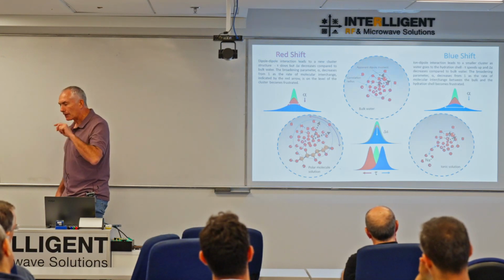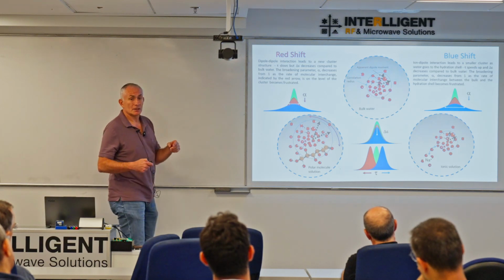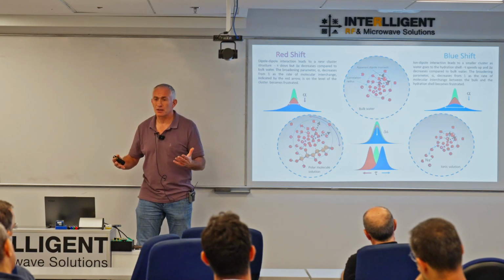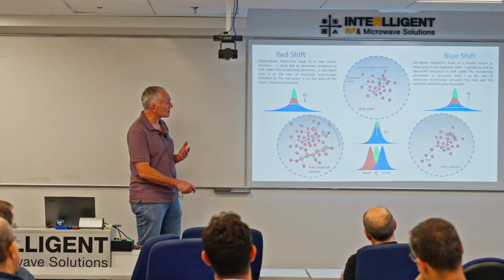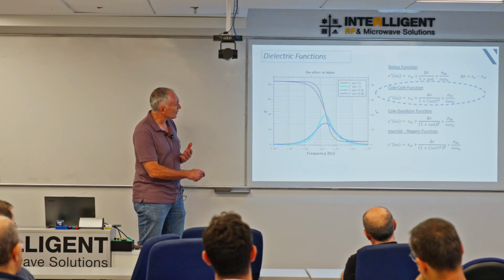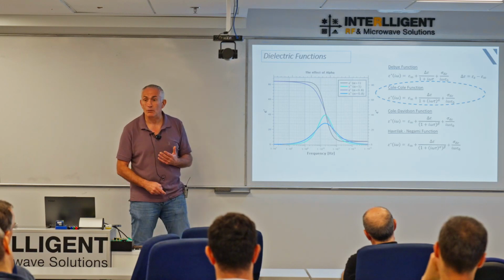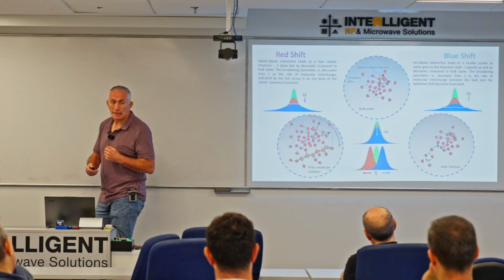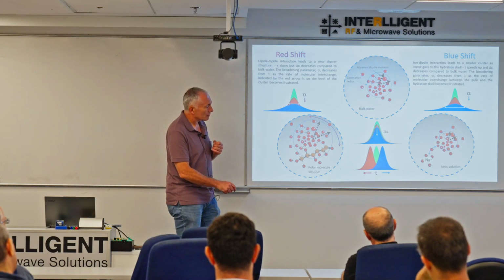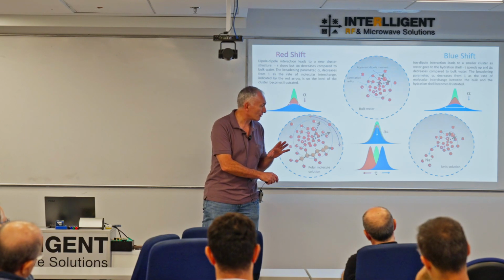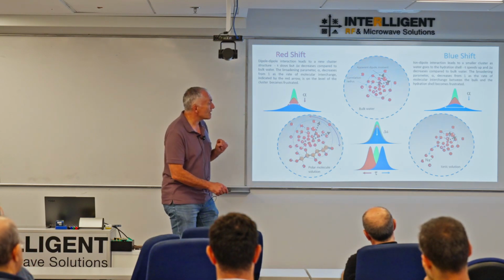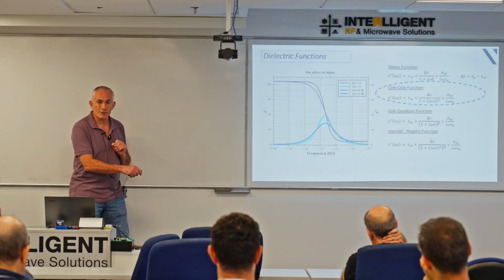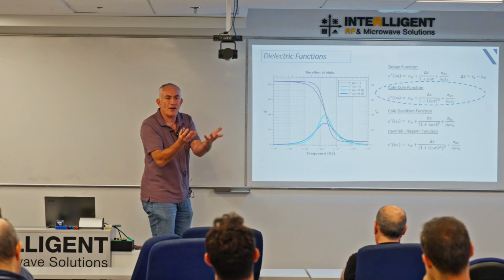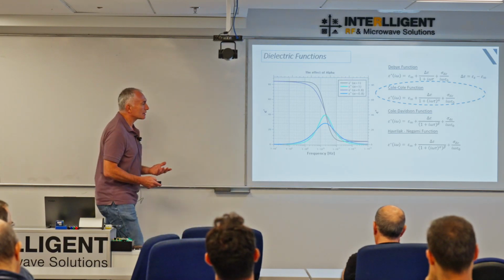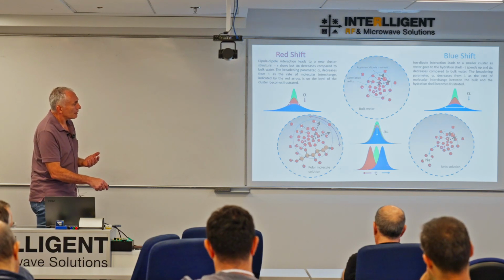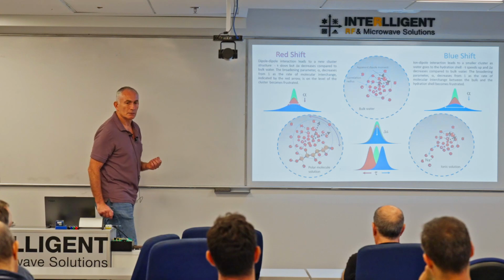But if I then start putting stuff into water, the behavior changes from that nice, easy Debye picture that I showed you. We see that as we put stuff in, the dielectric strength, this difference between here and here, goes down. Depending on whether it was an ionic substance I put inside a solvent, like salt, I'll see that the relaxation time, this characteristic frequency, will shift to higher frequencies, as though things are getting faster. And there'll be a broadening as well.